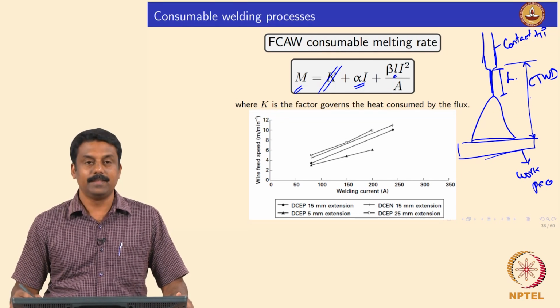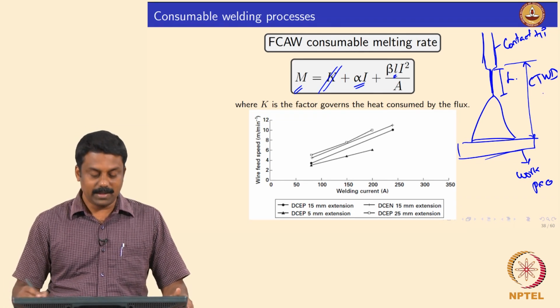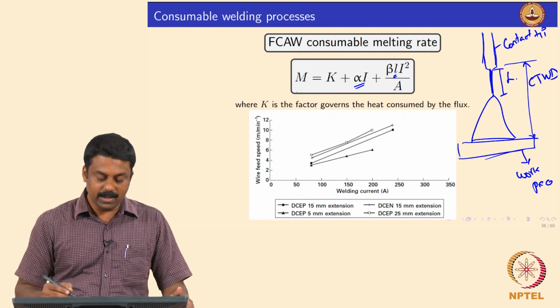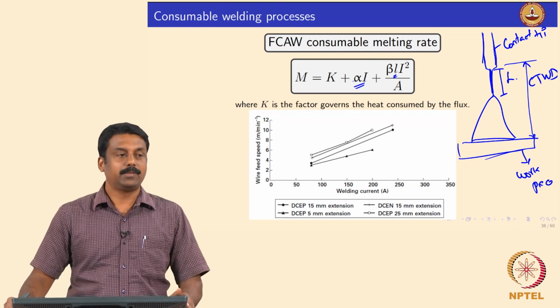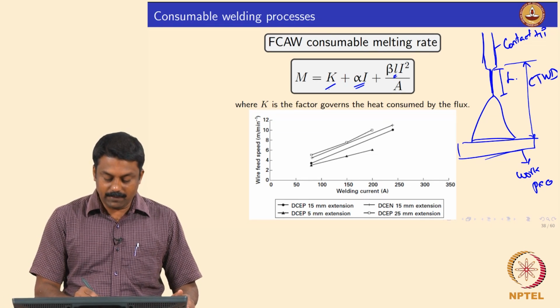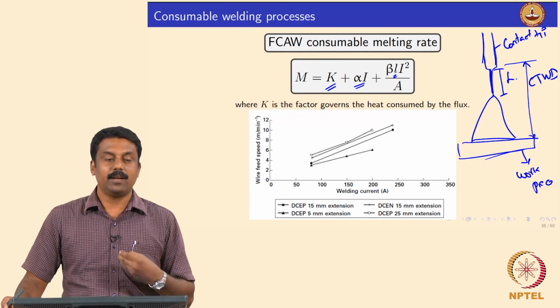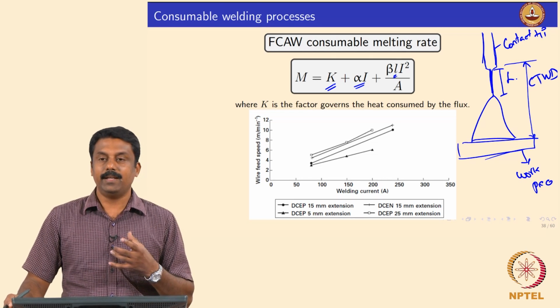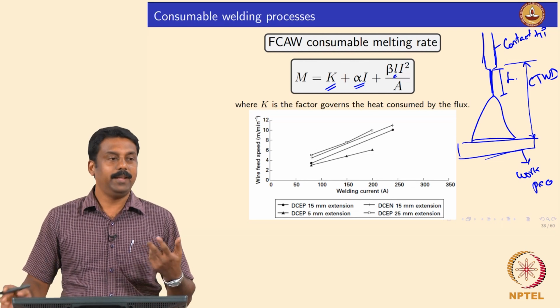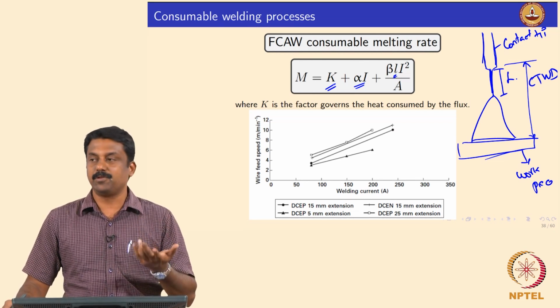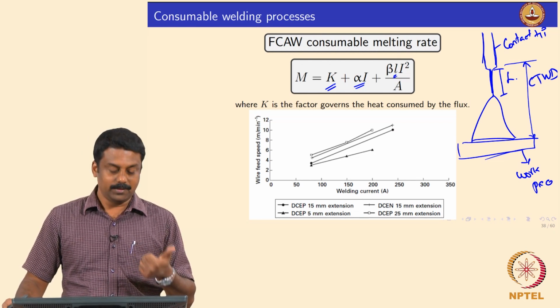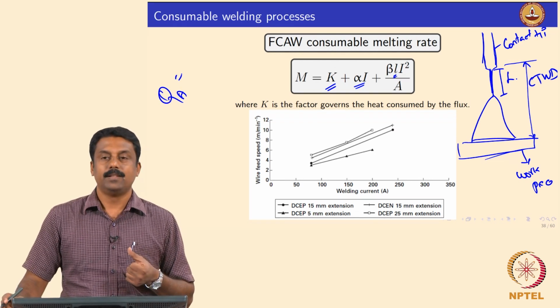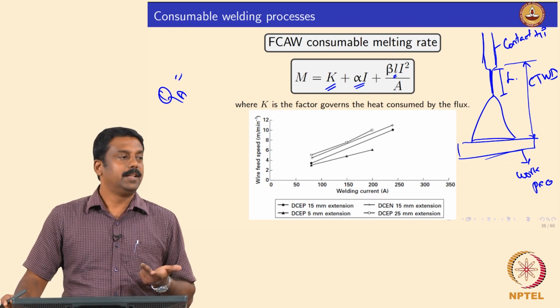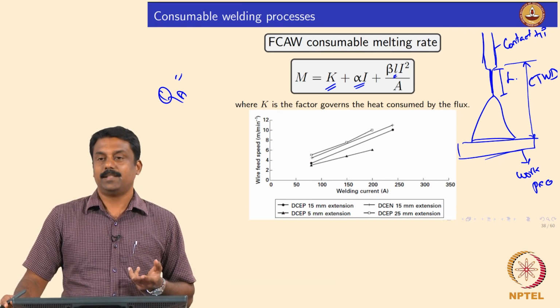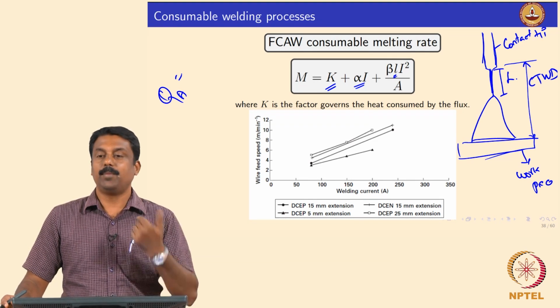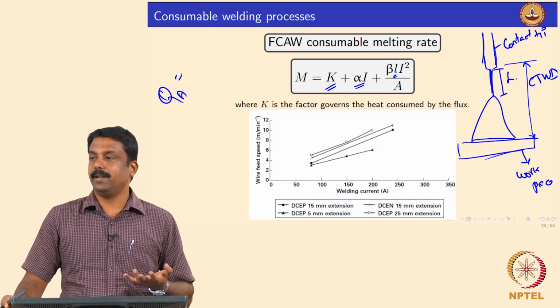Okay, if you are doing a constant arc length case at a given CTWD, then your L should be based on your melting rate, isn't it? So, in a conventional GMAW, we use an I plus I square relationship, whereas in this case we also have to have another term, because the heat is also consumed by the flux, isn't it? So, when we did the heat balance to calculate the melting rate, we looked at 4 important parameters, isn't it? If a consumable is an anode, the heat generated in the anode, that is QA, plus latent heat of melting, and then heat generated in the anode by resistance heating, and then the heat needed to increase the temperature of droplet to the droplet temperature. Okay, that is the heat balance we did to calculate the melting rate, right.